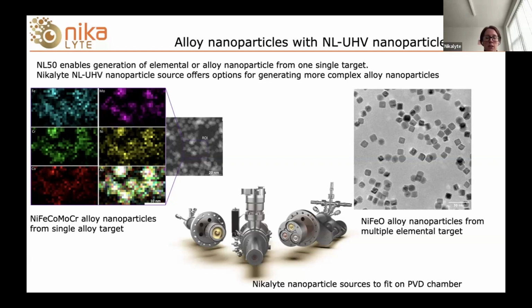So I've included here two examples of alloy materials that are generated using, in one case, a single alloy target, so nickel, iron, cobalt, moly, chrome alloy nanoparticles here generated using an alloy target. So it's possible to generate those with just one target. And in this case, we show that this X-ray image shows that we have each element present in those nanoparticles. So we have actually managed to reproduce the alloy composition of the target in the nanoparticles.